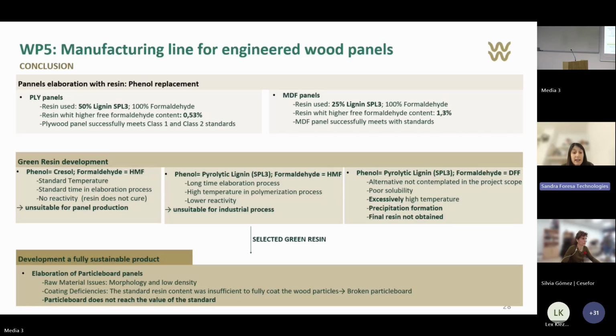We tried Cresol-HMF, lignin-HMF, and lignin-DFF, which was not initially contemplated. Due to precipitation during the process, the Lignin-DFF resin could not be produced. For Cresol and HMF, the resin reactivity was almost null, making it unsuitable for panel production. The lignin-HMF resin, despite the harsh conditions needed to elaborate it making it unsuitable for industrial process, was selected to elaborate fully sustainable panels since we could obtain it in the laboratory. So the 100% bio-based resin we chose was for elaboration of the wood chip panels.